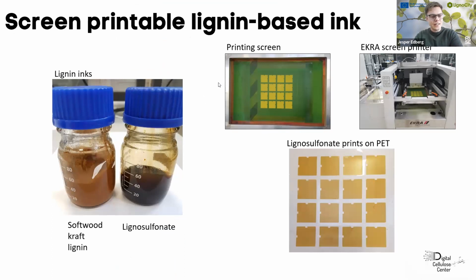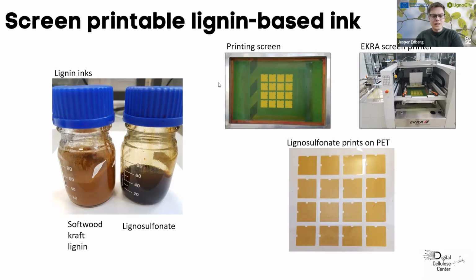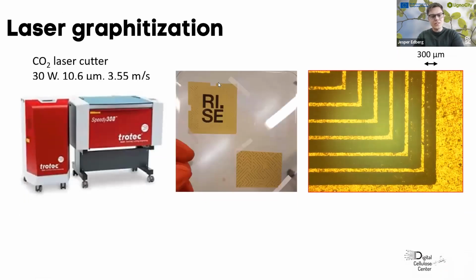Here you can see the lignin ink and also how this printing equipment looks, the frames with the pattern that we're printing, and how a pattern can look when we have printed it onto a substrate. And then we just use a commercial carbon dioxide laser to directly write the carbon tracks onto these lignin prints. And what's interesting about this technology is that the laser itself uses very low power. This laser is only 30 watts, and actually we only use 10% of the maximum power, so just something like 3 watts. And compared to the oven graphitization, where you have to reach maybe 1,000 to 2,000 degrees, it's very low power consumption. So in and by itself, that's also a step towards more sustainable production of graphite.